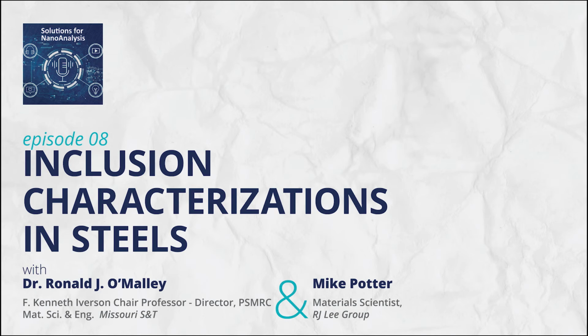But what's really neat is that we can see cases where a good job hasn't been done protecting the steel after all that work is done, and reoxidation has been allowed to occur. If oxygen is re-injected back into the system, you generate a whole family of new inclusions from that oxygen ingestment, and it actually reverts the inclusion population density function back to a curved distribution. We've been able to use the IntelliSEM's statistical capabilities to relate the shape of the inclusion population to identifying sites where contamination has taken place and oxygen is leaking into the system.